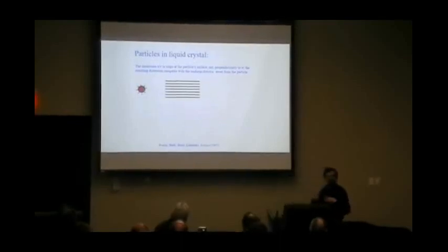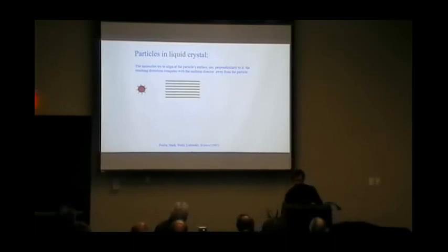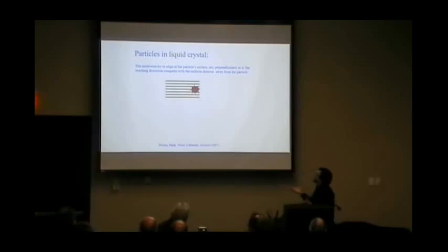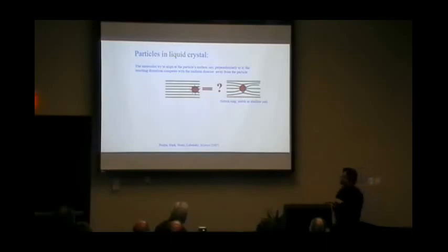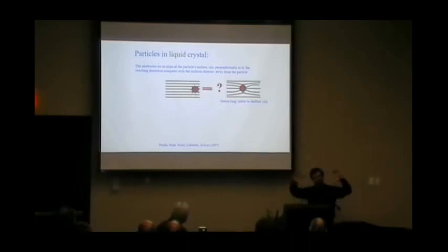So we can consider how these simple things translate into the combination of a colloidal particle and the liquid crystal. So the liquid crystal, let's just imagine that this is a uniform aligned cell, and we have a colloid that we place into the liquid crystal. I show this little hair on the surface of the colloid that signifies that this particular colloid wants to see the director being perpendicular to its surface. So how do you reconcile this local tendency to form a kind of hedgehog with the generally uniform far field in the director? You have to somehow combine the two, and the first solution, by the way, suggested here by Sergei, was to create the Saturn ring that would reconcile the uniformity in the far field and satisfy the radial direction at the surface.